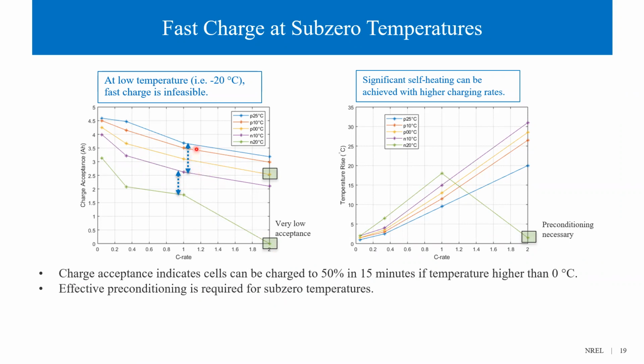Left figure shows the charge acceptance as a function of charging C rate and ambient initial temperatures. In general, charge acceptance becomes worse with higher C rate and lower temperature. At 0 degrees Celsius, the charge acceptance is 50% with a 2C rate, indicating the cell can be charged to 50% in about 15 minutes. However, charge becomes unacceptable with 2C rate at minus 20 degrees Celsius. To charge the cell at minus 20 degrees Celsius, effective preconditioning by warming up the cell is necessary. It's worth pointing out that self-heating should be considered to work with warm-up technology.